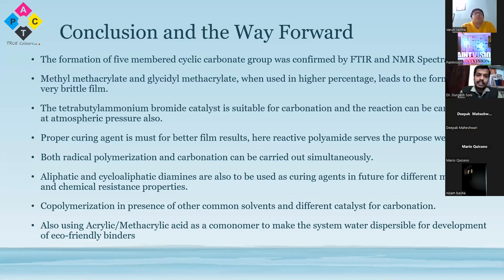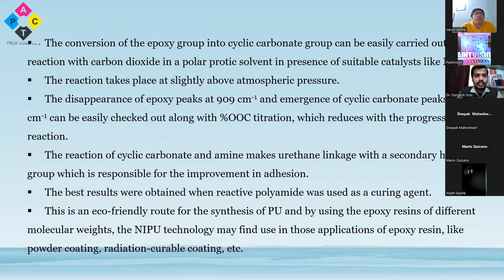Aliphatic and cycloaliphatic diamines can be used as a curing agent depending upon the requirement of the properties. And apart from this, if we incorporate acrylic acid or methacrylic acid in the copolymer, some water dispersible system can also be obtained, which may be the future work. And at 909 the epoxy peak reduces, and at 1800 the cyclic carbonate group appears. This is common in every reaction.